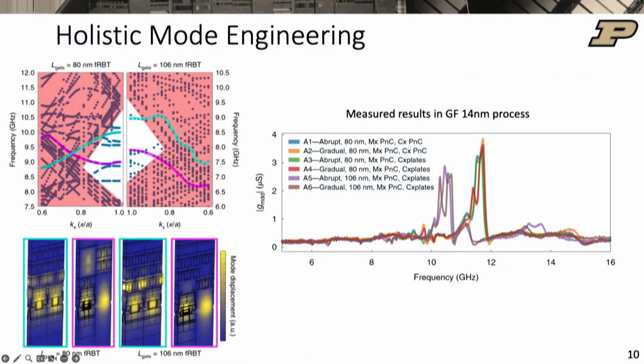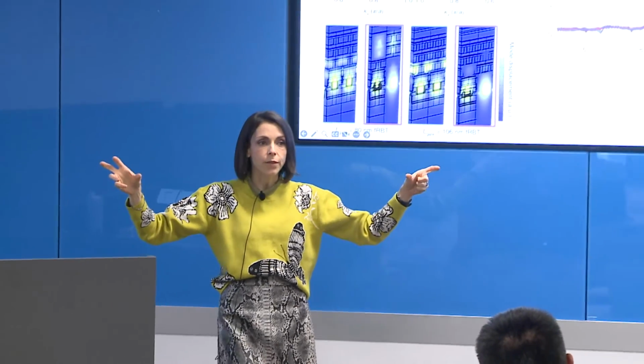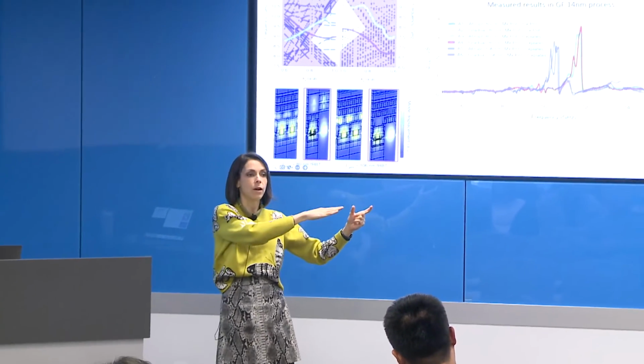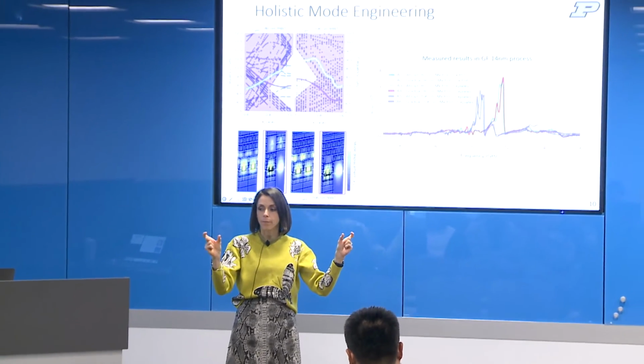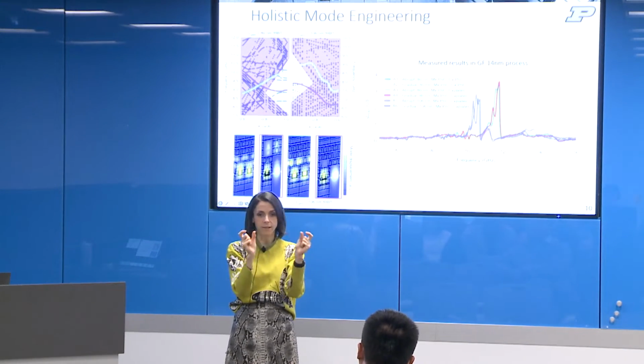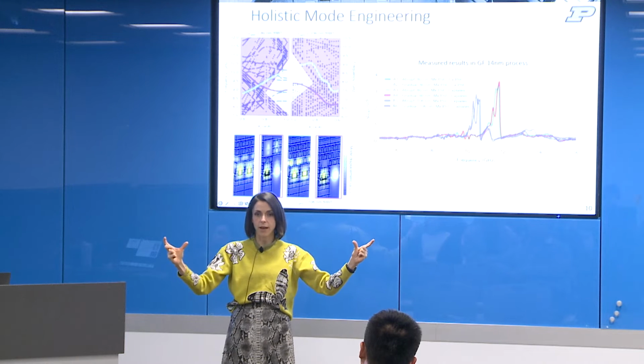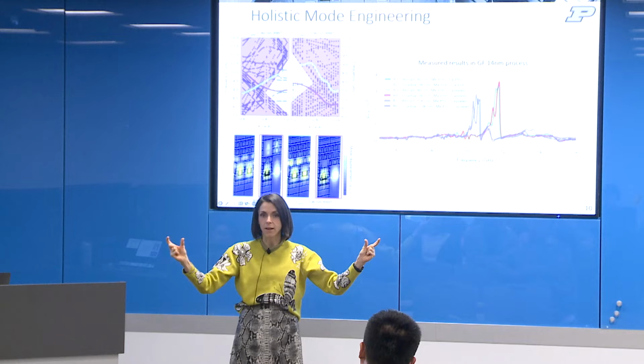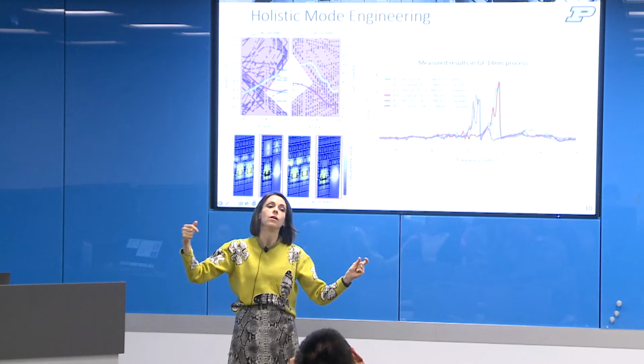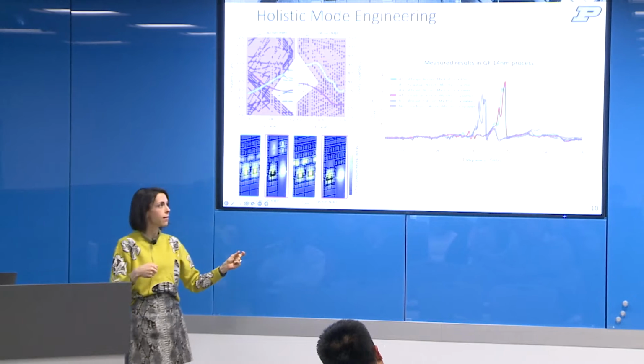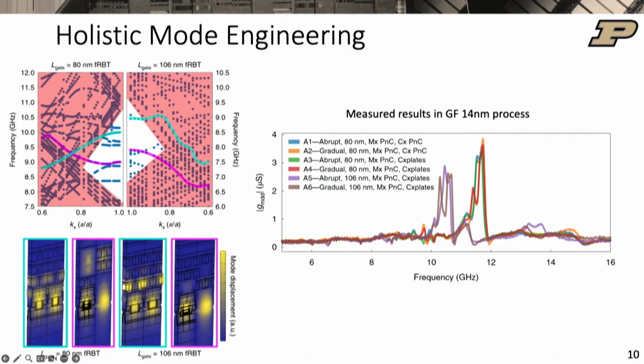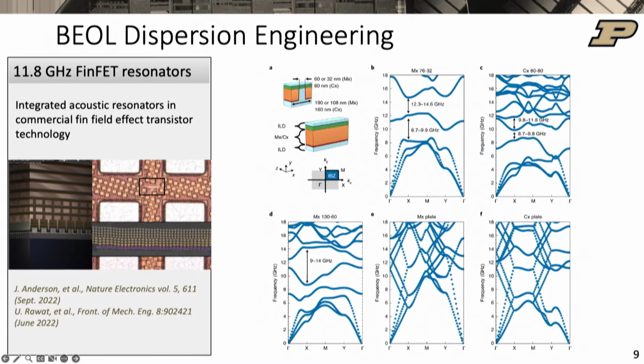How do we get lateral confinement? So in this case, the periodicity, you saw we have many, many periods in plane, right? And the reason for that is that I need to create that slow wave structure, but it depends on the unit cell in plane. If I change the length of each of those cells, the periodicity, I actually change the frequency that can propagate in that phononic waveguide.